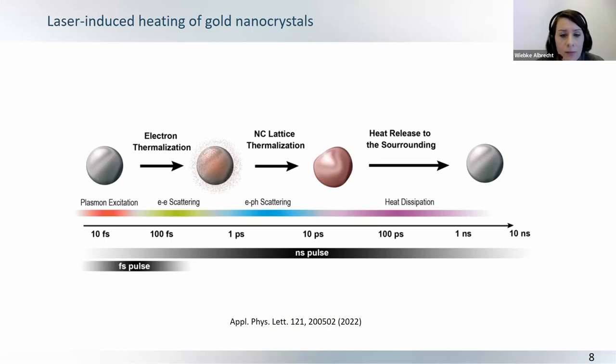Now it critically depends on how fast you actually deposit that energy. If you're coming with a femtosecond laser pulse, all of the energy is basically absorbed. If you come with a nanosecond pulse, so even longer, then you're basically competing also with cooling.